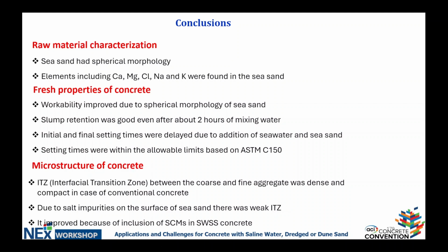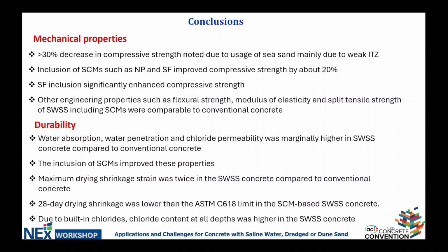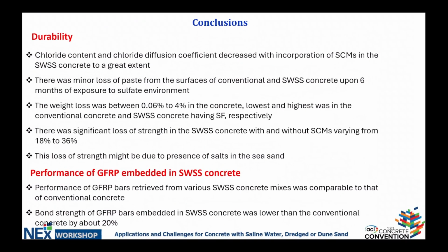In terms of microstructure, we have identified, and particularly the work that Dr. Kalim has done at the university, that the interfacial transition zone seems to be the culprit of some of the degradation of strength that we have seen. Mechanical properties, this is a repetition of the previous point. If you have an ITZ that is problematic, obviously this translates into less strength. Interesting in the compressive strength rather than the flexural strength. In terms of durability, I think the shrinkage can be easily corrected if you pay attention to what you put into the system. The part that is, in my mind, a little more concerning is the issue of the sulfate attack, for which we need to be cognizant and really make an effort to correct it.